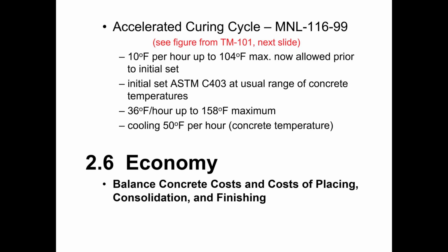So the requirements for accelerated curing are we can only raise the temperature of the concrete a maximum of 10 degrees per hour until the concrete reaches initial set, or until the concrete reaches 104 degrees Fahrenheit if it's pre-initial set. Okay, so we can heat the concrete, but only 10 degrees per hour up to a maximum of 104 degrees Fahrenheit unless the concrete has reached initial set. If it's reached initial set, then this requirement no longer applies and we can heat the concrete up more quickly. Initial set, just as a reminder, is 500 psi.